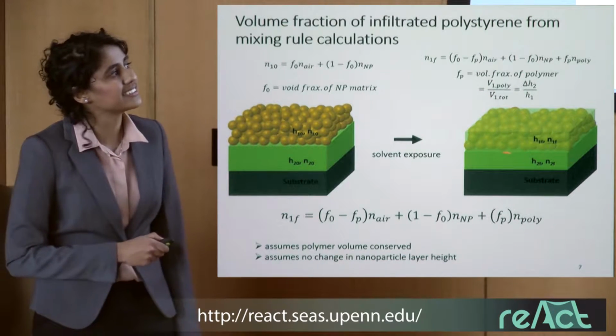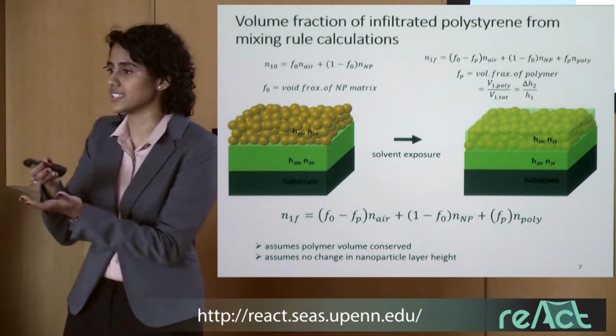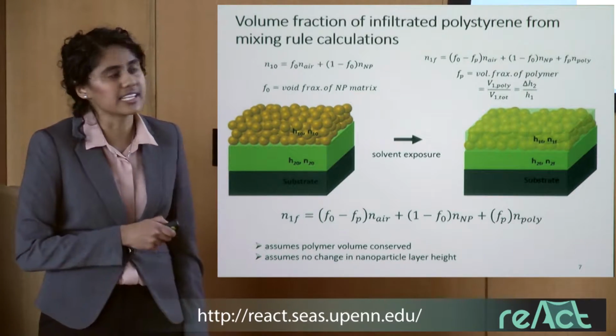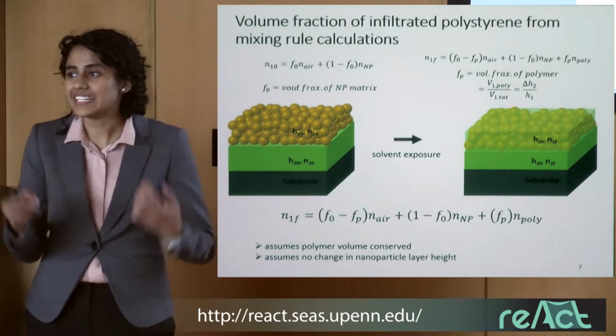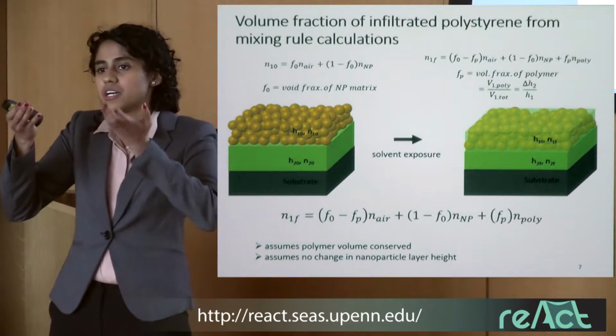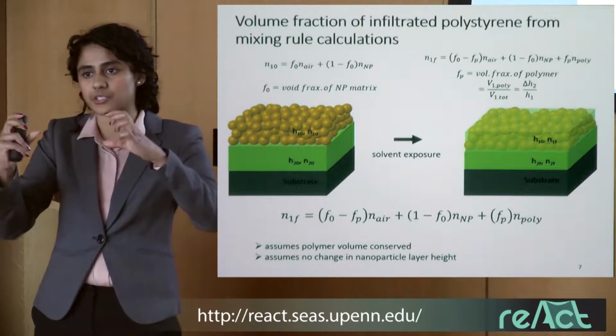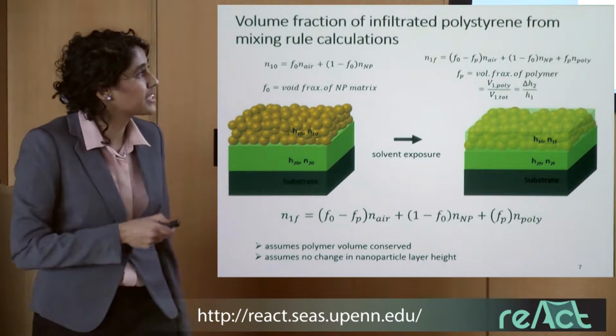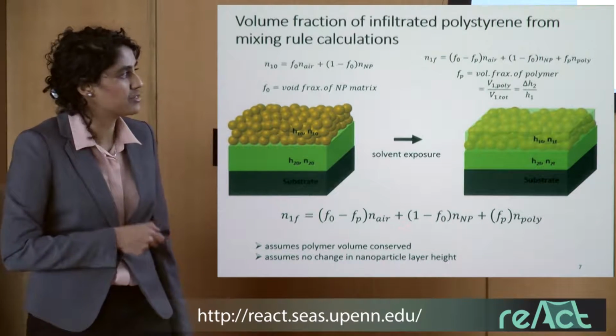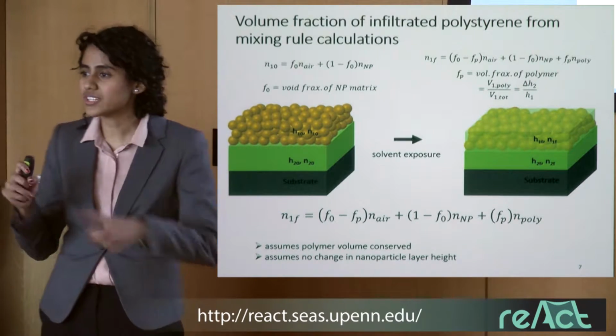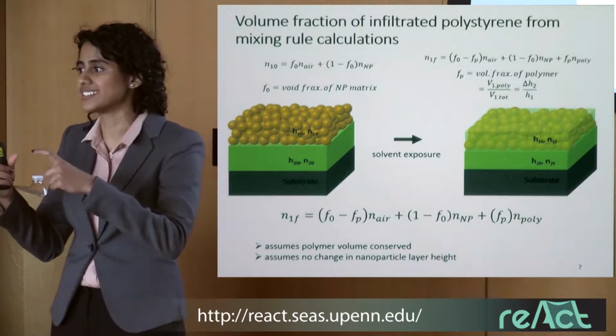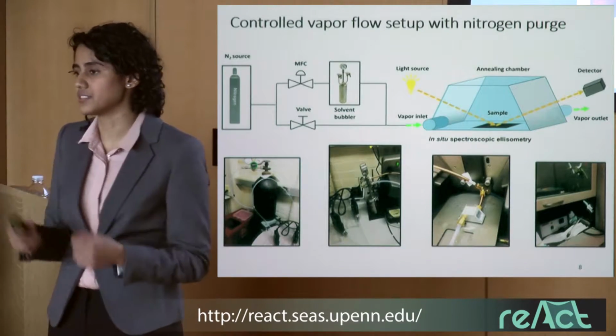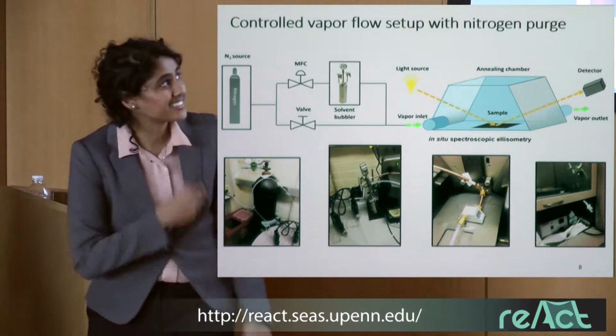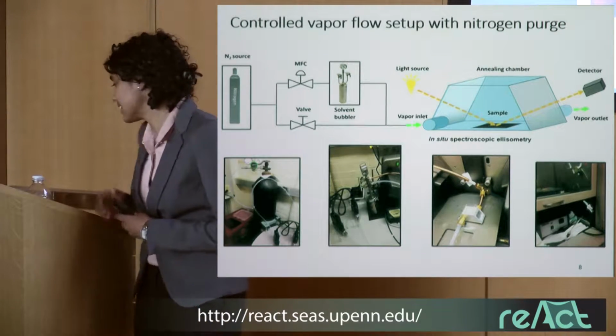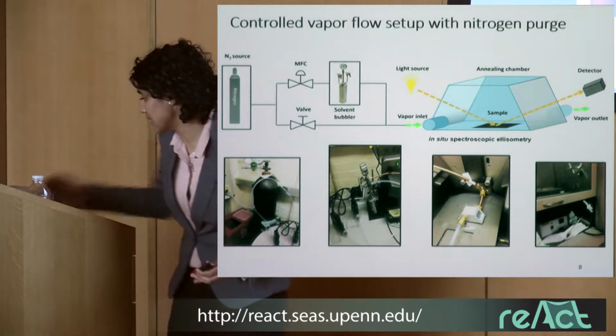So what you see is a decrease in the polymer layer thickness and an increase in the refractive index of the nanoparticle layer thickness, indicating that some of the polymer has left the bottom layer and infiltrated into the nanoparticle packing. And you can use conservation of polymer volume to calculate what the volume fraction of polymer is in your nanoparticle layer after infiltration.